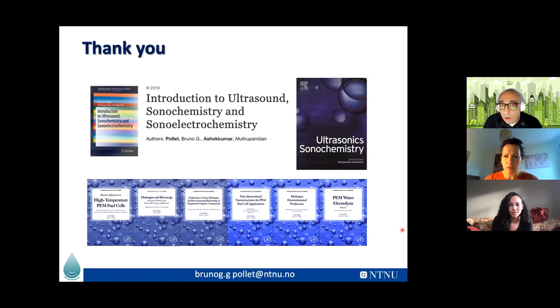Rodolfo has a question: how do you scale up ultrasound technology? This is a very good point. It's feasible. There was a company that I used to work for before I left the UK for Norway, based in Swansea, where they actually scaled up sono electrochemical systems for the water treatment industry. And they've done it very well. They were using ultrasonic transducers and doing electrocoagulation, to promote not only the dissolution of the anodic electrode material, but also mass transfer. We actually got some very good data.